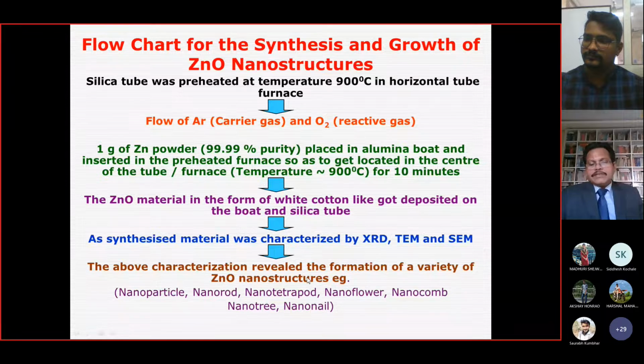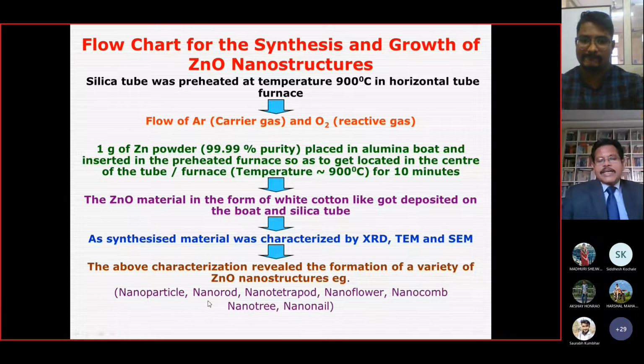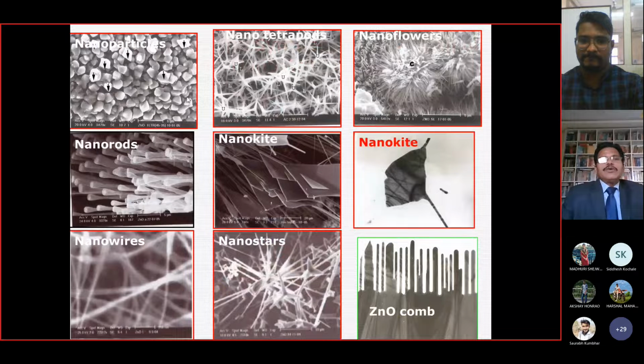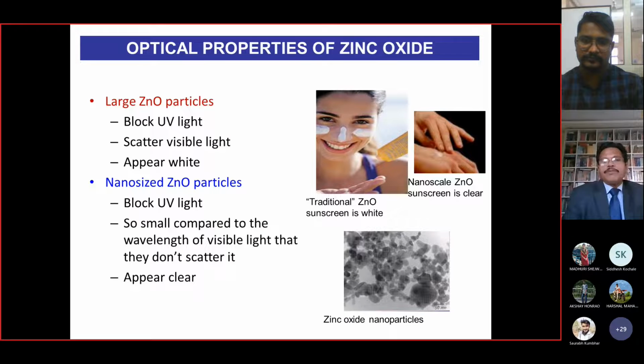After taking the morphology by SEM, we obtain nanomaterial with a nanorod-like structure, nanotetrapod, nanoflower, and nanocomb-like shapes, shown here in this slide. So these are the different images obtained for the surface morphology of zinc oxide. Here it looks like nanoparticles. Here it looks like nanotetrapods, nanoflower-like structure, nanokite-like structure. See these nanorod-like, nanowire-like, star-like, and comb-like structures. So the different nature of this zinc oxide is shown here, and we obtain such types of material.